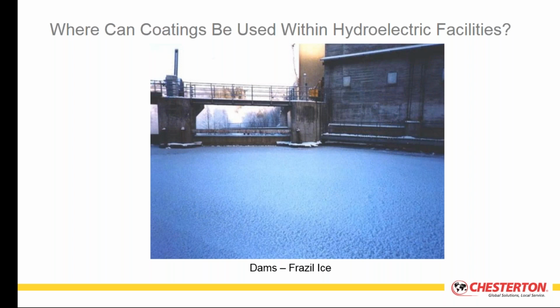The actual dams themselves, sometimes you're dealing with the nosings of the dam, particularly in northern climates where they have icing structures and what we call frazil ice. Frazil ice will act like an abrasive compound and wear away the weak concrete layer until it exposes the aggregate, and the aggregate will start to pop out. When the aggregate pops out, the underlying rebar can be impacted, and you're going to see accelerated spalling corrosion and more structural damage. So it's important whenever possible to provide coating systems on the upstream areas where frazil ice damage is prone, to provide a protective layer on top of the concrete and prevent that type of damage.